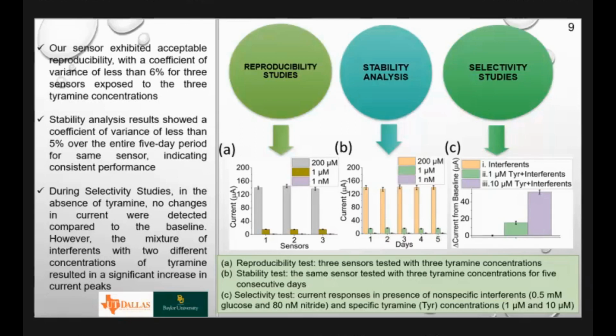We also tested the selectivity. Because it is a urine sample, the common interferents in urine are basically nitrite and glucose. In typical healthy individuals, the concentration of glucose is about 500 micromolar, and nitrite is about 80 nanomole in urine. So we have those as interference, and here it shows that we could see almost no interference, with 1 micromole tyramine and with 10 micromole tyramine. So this shows that this polytoluidine blue based detection shows good selectivity over common interferents in urine.